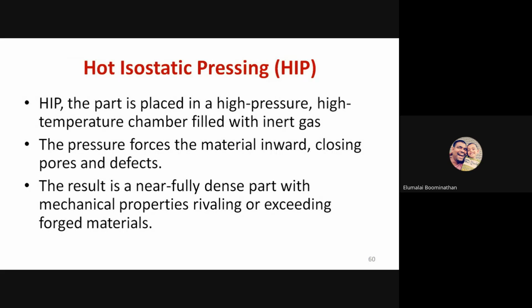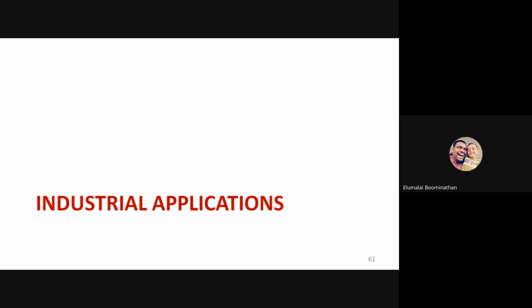HIP is very energy intensive, but for producing defect-free and long-lasting parts, HIP ensures that the part is highly improved in terms of removal of defects inside the component, whereas mechanical and other surface treatments only remove defects or improve the surface finish, and hot isostatic pressing removes the pores inside the component also. Now we'll discuss a few industrial applications.